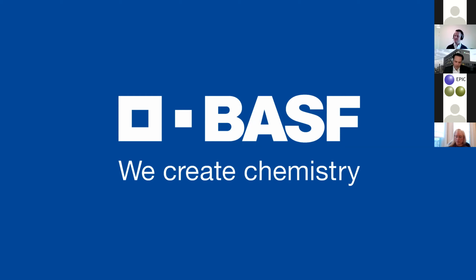One last question, because you mentioned PET, PMMA, PC, especially when it comes to UV lacquers on such substrates, we find good solutions on PET and PC, but few for PMMA. Is there a chemical reason for that? Yes. If you have a formulation, normally you put ingredients in there which attack the surface. If I may, to make it very general and quick, we can talk offline more if you want. For PET or PC, it's easier to attack the surface or to break certain bonds and to make reactive species than on PMMA.